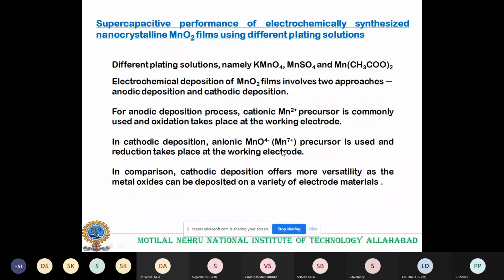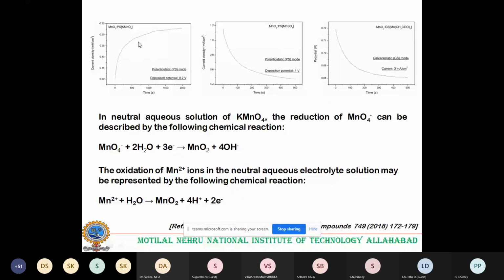This is the same thing which I discussed earlier also. For KMnO4, I will put only one result, which is the best. For manganese sulfate, we observed that the potentiostatic mode is the best one. Here also the potentiostatic. And in the manganese acetate case, we find the galvanostatic mode is more preferred. So only those deposition graphs we quote here. And what is the reaction mechanism? In the case of KMnO4, we have already discussed this result. For manganese sulfate and manganese acetate, this is the reaction mechanism going on: the oxidation of Mn2+ occurs, and we got the film of MnO2.